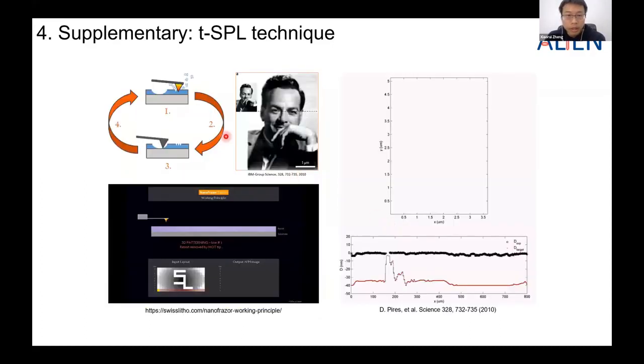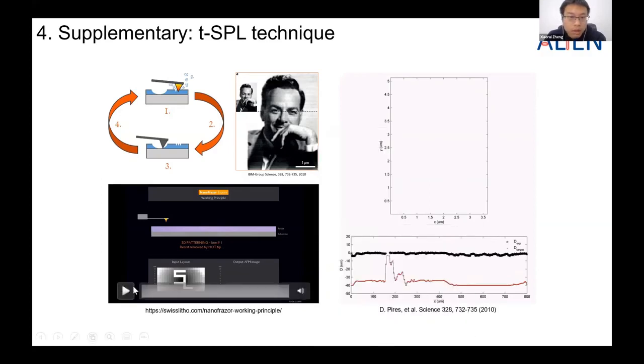Okay. And one feature I would like to show here is the closed loop lithography for NanoFrazor. So if you look at this image here, when the tip is patterning the polymer from the left to the right, we turn on the heater so that the polymer can be patterned. But when the tip is scanning back from the right to the left, we turn off the heater. The tip is behaving as a normal AFM to map the structures we have just patterned.